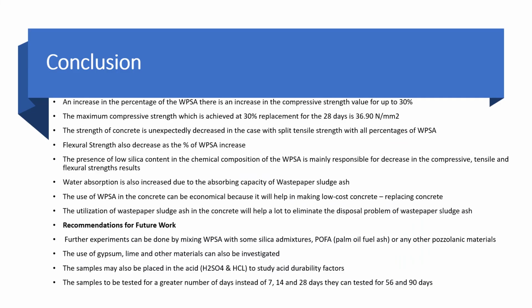So from this study, we conclude that waste paper sludge ash has a positive impact on the concrete compressive strength, but there is a negative impact on the split tensile strength and also on flexural strength. Water absorption also increases with the use of the waste paper sludge ash. So clearly we can use the waste paper sludge ash where we only consider compressive strength, and it can also help us to reduce the cost of the concrete and its environmental impact. Further experiments can be done by mixing waste paper sludge ash with some silica admixture.